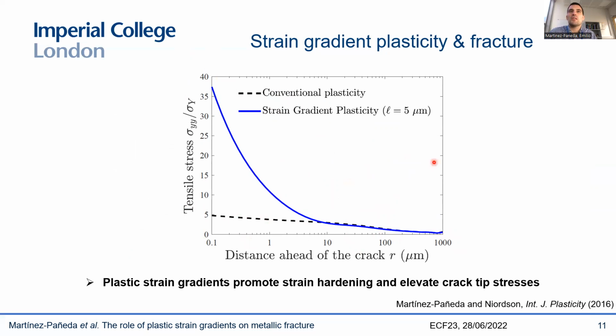And effectively, what you see is that far away from the crack tip, both conventional plasticity and strain gradient plasticity agree. However, as you approach the crack tip, then GNDs start to dominate over statistically stored dislocations. You have a strong influence of this plastic strain gradient. You have those dislocation hardening mechanisms kicking in. And as a result of that, you get a very significant stress elevation.